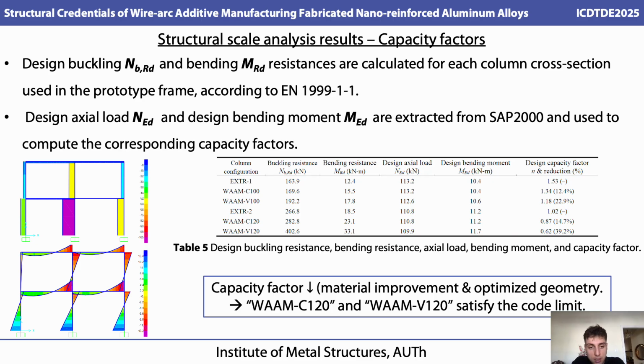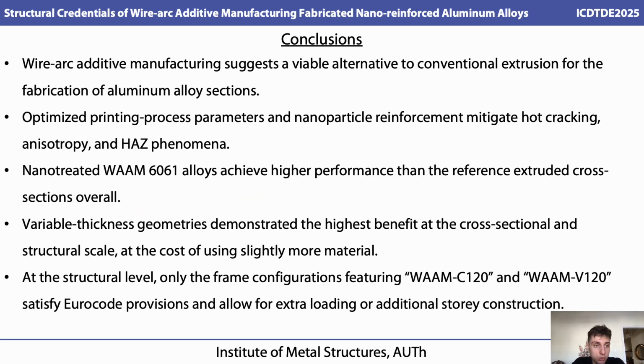As you can see, capacity factor decreases due to both the material improvement and optimized geometry. Sections WAAM-C120 and WAAM-V120 satisfy the code limit, Eurocode's limit. So, overall, and to conclude, wire-arc additive manufacturing suggests a viable alternative to conventional extrusion for the fabrication of aluminum alloy sections.